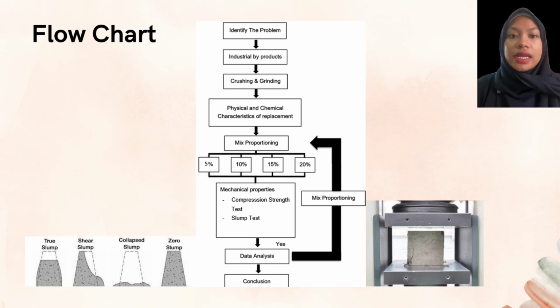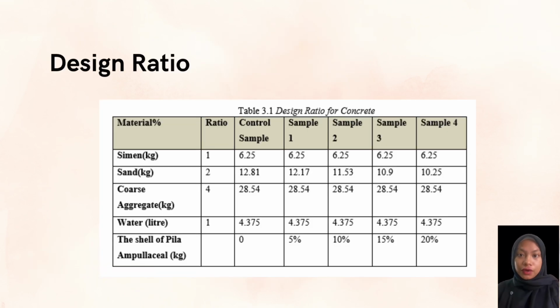Then we do the data analysis. If it's good data analysis, we can proceed to the conclusion. If it's not, we need to go back to mix proportion and we need to repeat the mechanical properties with the compression and slump test. For design ratio, we use 1 for cement and 2 for sand and 4 for the coarse aggregate. So we use 1, 2 and 4.